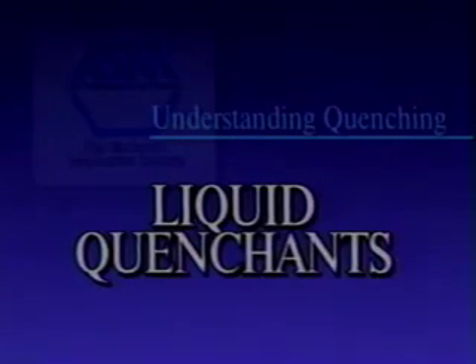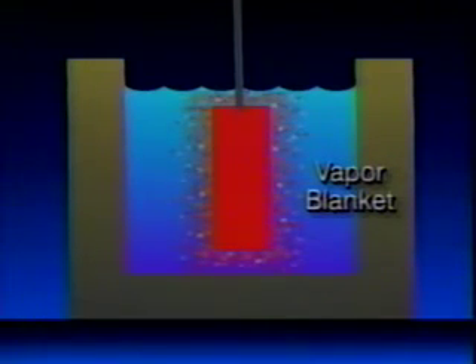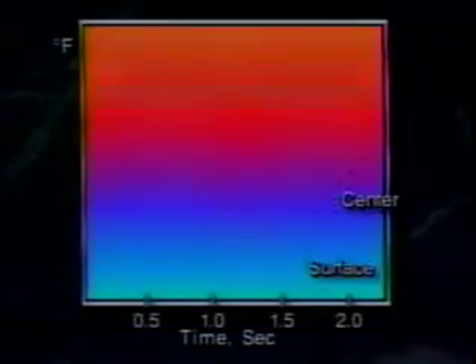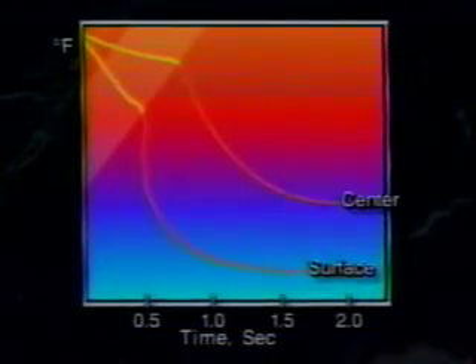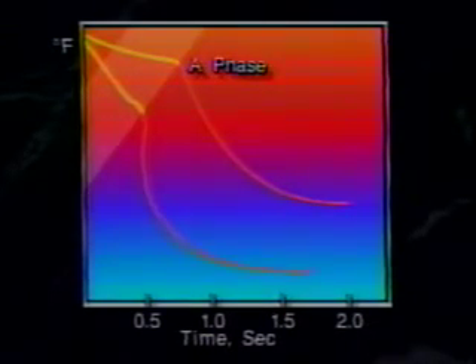Liquid quenchants. When quenching in liquids, certain things occur that do not occur in other quenching media. One thing peculiar to liquid quenchants is the vapor blanket. This is the first of 3 stages of quenching, the A phase. When a hot piece of metal is plunged into a relatively cool liquid, the liquid in contact with the metal boils instantly and vaporizes. A vapor blanket or pocket of bubbles forms around the part. This is the vapor blanket, which tends to insulate the workpiece from the quenching liquid. This vapor blanket can affect the severity of the quench. During this A phase of quenching, the cooling rate is extremely slow.